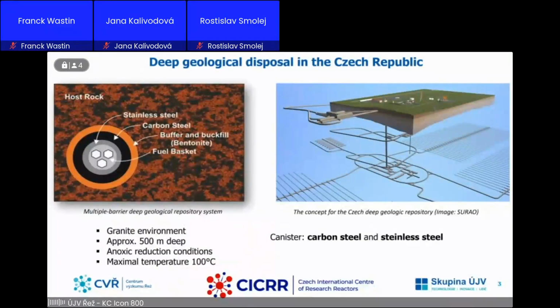So deep geological disposal in Czech Republic is based on the Swedish KBS-3 concept with certain modifications. The deep geological repository will be constructed in a suitable granite environment at a depth of 500 meters with a designed temperature of 100 degrees Celsius, where we expect long-term anoxic reducing conditions. The canister will consist of two layers. The first inner layer of carbon steel, and a second outer layer of stainless steel. As buffer and backfill there will be Czech bentonite, representing calcium-magnesium bentonite.